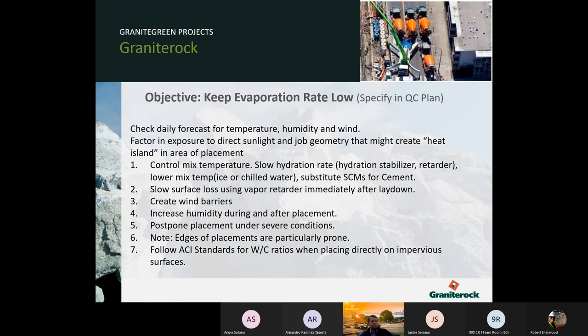Decrease the potential for wind using barriers. Increase humidity if you're able to. And also postpone placements until better conditions. Note that edges of placements are the largest area potentially prone to issues. And also follow ACI standards for correct water cement ratios when placing on impervious surfaces, such as visqueen barriers.